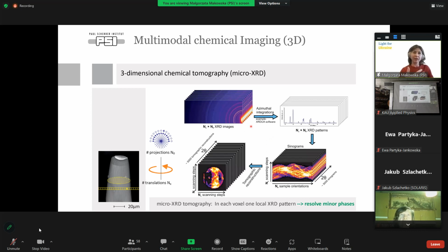If we do it with diffraction, of course, we first measure diffraction rings, the images of diffraction rings, which first we need to azimuthally integrate. And then the further procedure is the same. Based on the patterns for each measured pixel, we construct sinograms, then we perform tomographic reconstruction, and then we can have a 3D image of crystalline phase distribution.